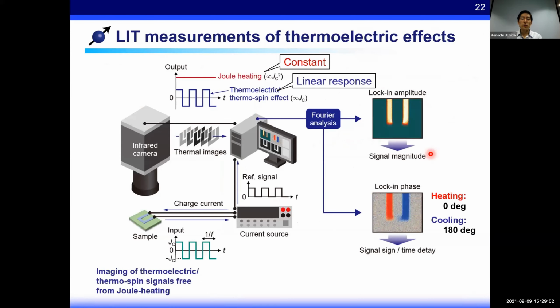So to realize the direct observation of the anomalous Ettingshausen effect using this technique, we measure the spatial distribution of the infrared radiation thermally emitted from the surface of the sample while applying a square-wave modulated AC charge current to the sample. Importantly, the offset of this AC current should be 0. By extracting the first harmonic response, we can separate the contribution of thermoelectric effects from the contribution of Joule heating, because the Joule heating generated by this square-wave modulated AC charge current is constant in time. So only the thermoelectric contribution can be detected. By combining this technique with magnetic-field-dependent measurement, we can visualize the temperature distribution induced by the anomalous Ettingshausen effect.